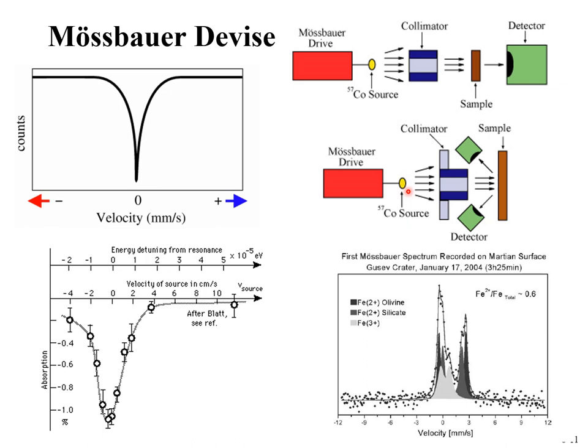Here's another source, an example where Moessbauer spectroscopy is done on iron, where another collimator, a sample, the sample could be a surface, and detectors are off at angles. So again, you should see scatter. A decrease in scatter as a function of this vibration would mean that some of the photons have been absorbed by the materials. This was used on the Martian surface.